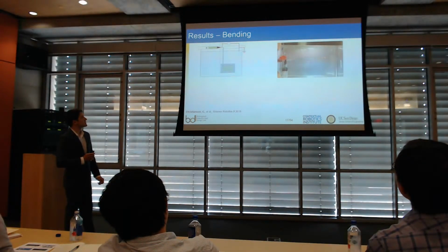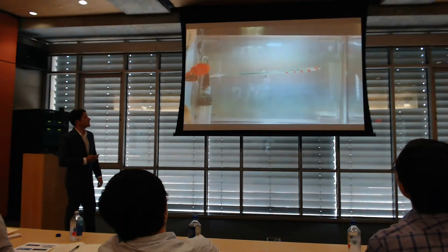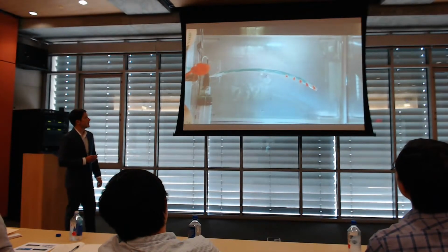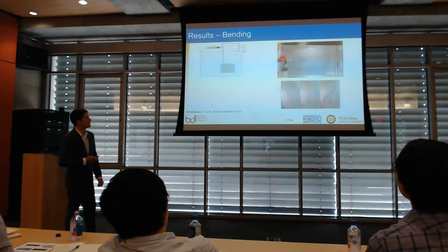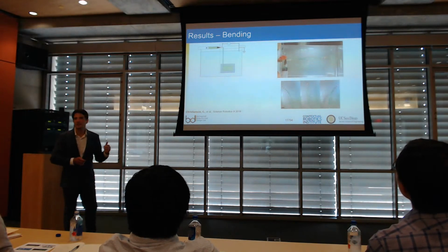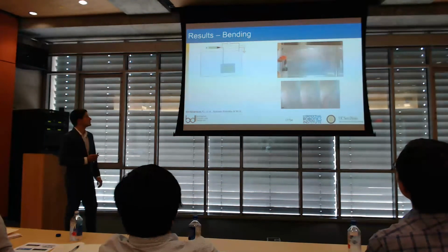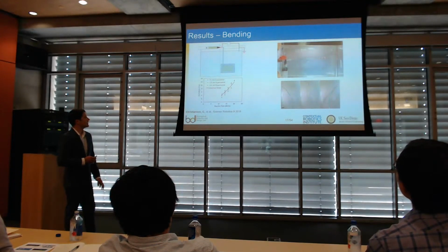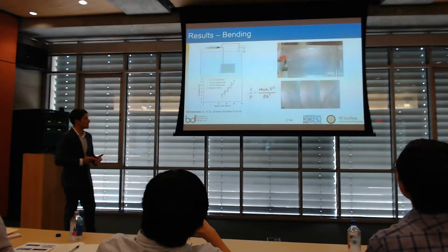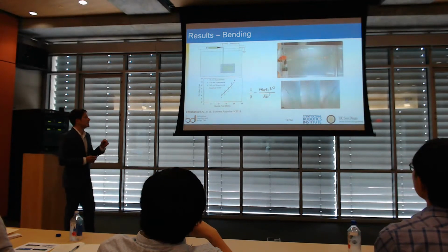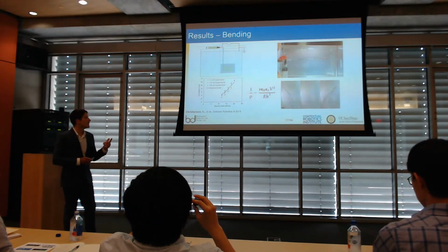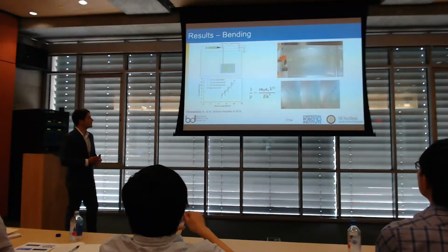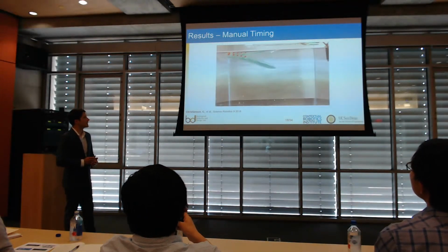To test this, we put it on a simple test stand and then apply the voltage to make it move. We can control the direction of bending based on which pouch we apply voltage to, and we can control the magnitude of bending based on the amount of voltage that we apply. Then we also compare this to an analytical model that shows that the curvature should be proportional to the Poisson's ratio times the permittivity times the voltage squared, divided by the Young's modulus and the cumulative thickness. And our experimental results match up pretty well with the model that we have.